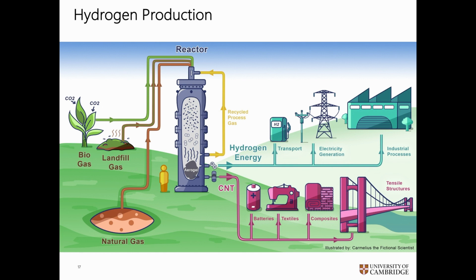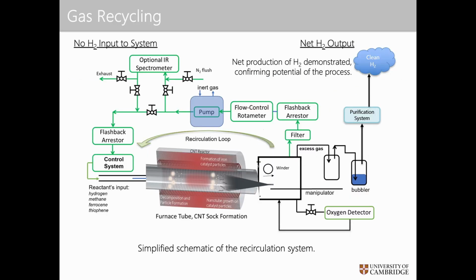In other words, we can take the gas phase species that come out at the exit of the reactor, recycle them back in, and only put in new carbon and, frankly, a much lower fraction of iron, and we can get substantially the same process to run. So that's what it looks like in a nice diagram. This is what it looks like in a messy schematic here. But basically it's the same process where one is winding up the nanotubes, and then you bring the gas out, and then you ultimately feed that back around. We were doing some spectrometry as we do it, just to look at what is in that gas, and then feeding it back in the front end. And then at the outlet of this, you also get clean hydrogen production. And so that we've now demonstrated.